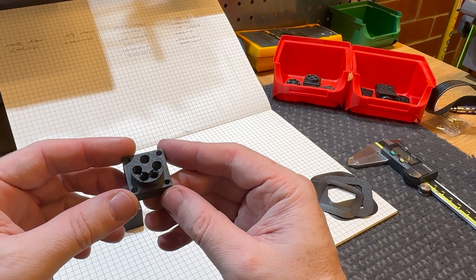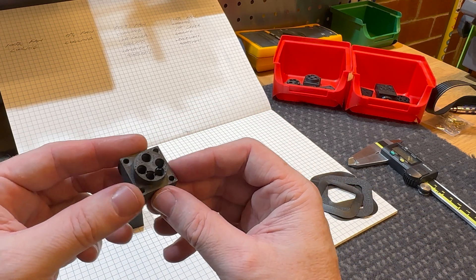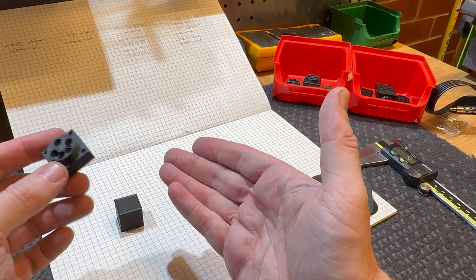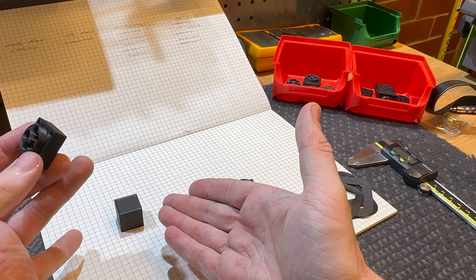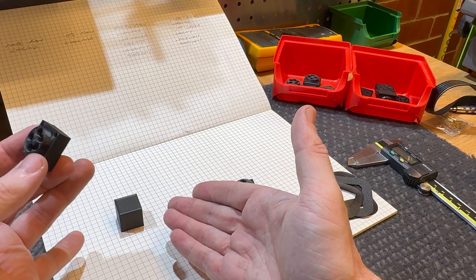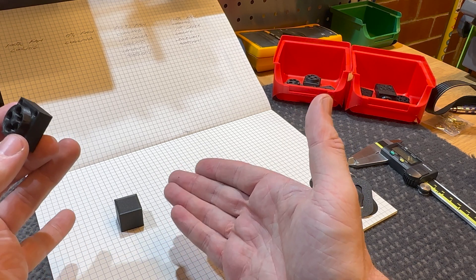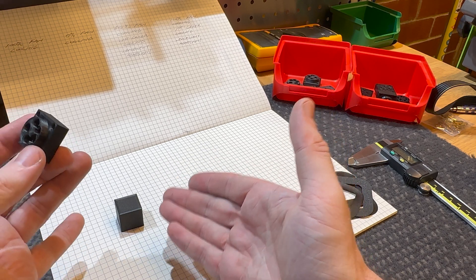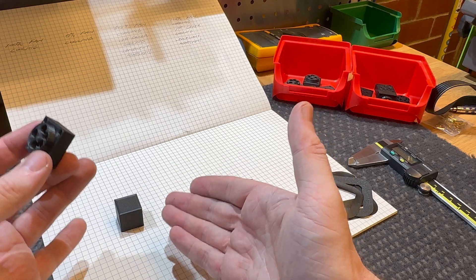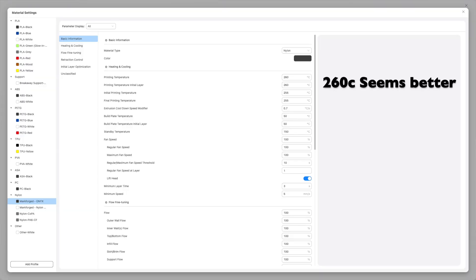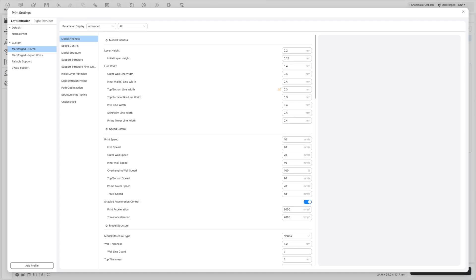To an actual part print, because I was so happy with that test cube. That was a 50-degree bed temperature and a 270-degree hot end temperature, and I'll overlay some Luban settings again just for your reference, but you're going to have to play around and mess around with it.